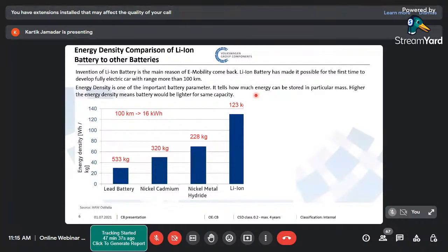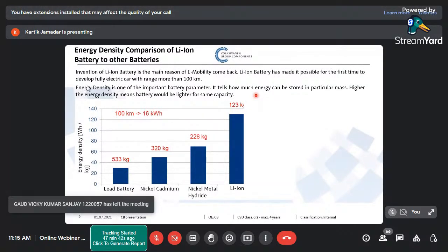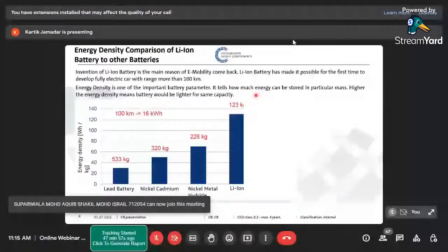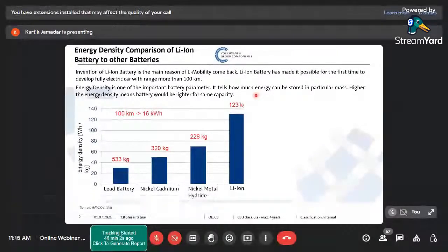So normally we give a ratio that 1 kilometer needs 1.2 kilograms of battery weight. This was about 10 years back. Now the ratio has gone to 1 kilometer per 0.8 kilogram of battery. So as energy density increases, we get more and more kilometers for the same amount of mass. That's why we can say that lithium ion cell technology has made e-mobility possible. Otherwise, it was unthinkable with so much weight from the other kinds of batteries.